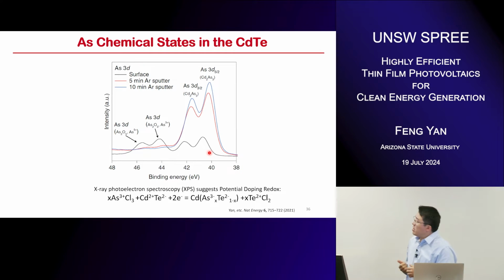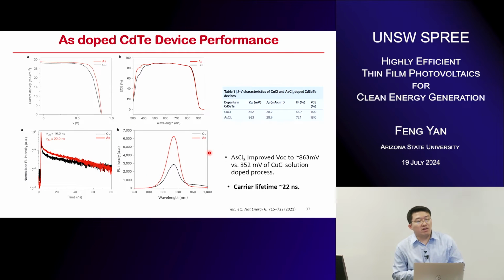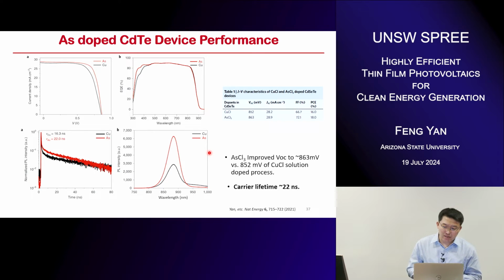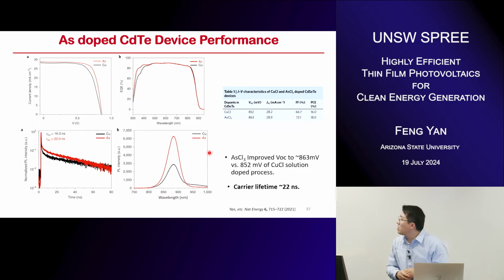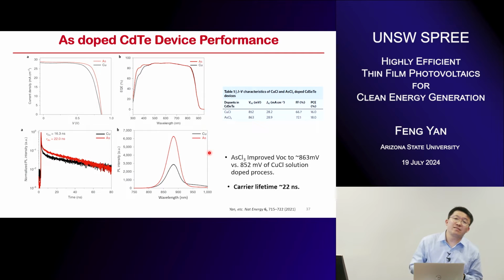And if the arsenic 3 plus works, this will open another way to use other group 5 dopants with different precursors. Further device characterization demonstrates that this arsenic chloride can perform similarly to the copper chloride, but with different environment protection. The device is pretty nice, around 18%. This is also demonstrated in different device architectures, with a carrier lifetime of more than 20 nanoseconds. But we'll see it's not as high as expected, because we are trying to further demonstrate high VOC, right? So this is the first try at using an ex situ diffusion process to realize group 5 doping.